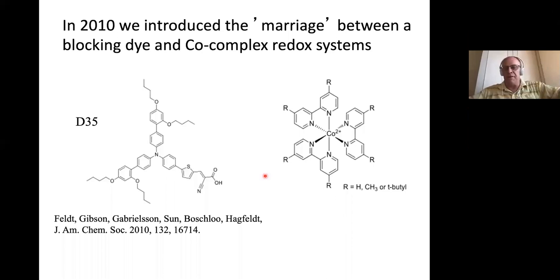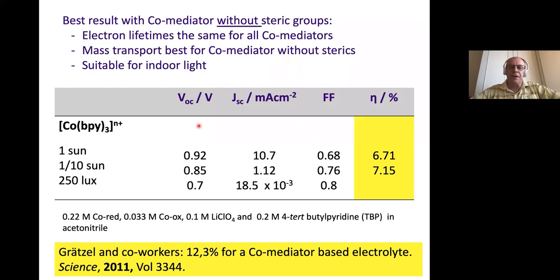So when we published this, it was really a breakthrough. We were up to 7% efficiency with these cobalt complexes. And the most important thing was fundamentally that we had a very high voltage, 0.9 volt, which we compare with iodide, which is typically 0.7. So we gained 0.2 volts. So that meant that we had really closed the gap of losing potential between regenerating the dye from the redox couple. So this showed us that indeed, if you passivate the surface, we can do other complexes. So this became quickly an interesting topic.